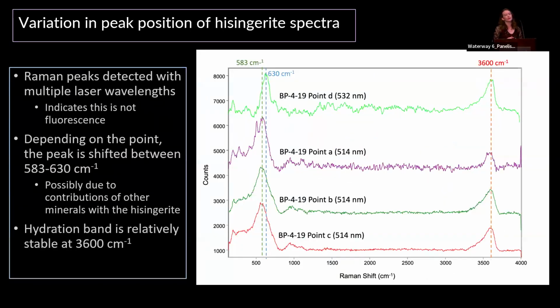And I just wanted to make sure that these were indeed Raman peaks and not fluorescence because of the broad nature of the peaks. And so I did this analysis using the 514 nanometer excitation wavelength and also 532. And we saw that these peaks were still there with both wavelengths. So that was a very good sign.